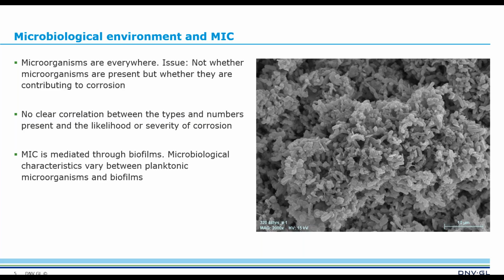One of the key things to keep in mind is that when it comes to MIC, what's most important is the biofilm that grows on the surface of a pipeline. We're interested mainly in pipelines in our work, but this is true of any structure or item that's suffering from corrosion. We want to know what's present in biofilms. You can do tests on a fluid like oil or water that's being transported through your pipeline and see what microorganisms are floating around; those are your planktonic bacteria. Those are important, but what's really important is what's happening on the surface. So a lot of our effort is focused on looking at what's growing on surfaces and how biocides or other mitigation efforts influence those biofilms.